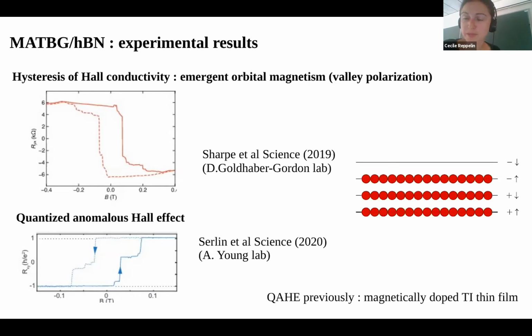Yeah, it's probably important to specify that previously quantized anomalous Hall effect had been observed, but in a very different setting. This is an observation that dates back to, I think, around 2013 or so. And the material was very different. What they did is they took some thin films of topological insulators. So the topology was coming from spin orbit coupling in those materials, and then they doped them with transition metals, so impurities that explicitly break time reversal symmetry. Here, the origin of the time reversal symmetry breaking is very different. There's no doping. It's spontaneous, and it's a material with only carbon atoms.